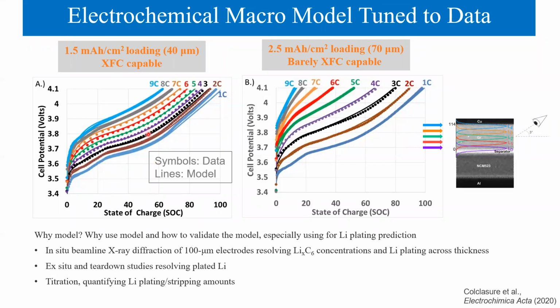Cell with low loading withstands extreme fast charging performance remarkably well, even up to 9C constant current charging, with high charge capacity, high Coulombic efficiency, and very little lithium plating. For moderate loading cell, the 6C CC charge capacity is poor, with a significant amount of observed lithium plating. The electrochemical model has been used as feedback to experiments and